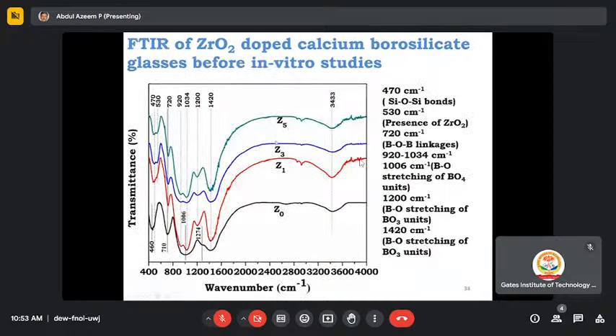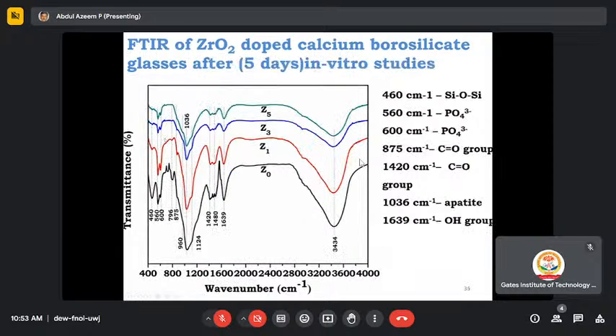And similarly, this is the FTIR before immersion of your material. So this tells about the functional groups of your material. Now after immersing your material into SBF, you can see a few peaks, 560, 600. The doublets indicate that this is related to calcium phosphate. So this also confirms that there is a hydroxyapatite layer formed on the surface.